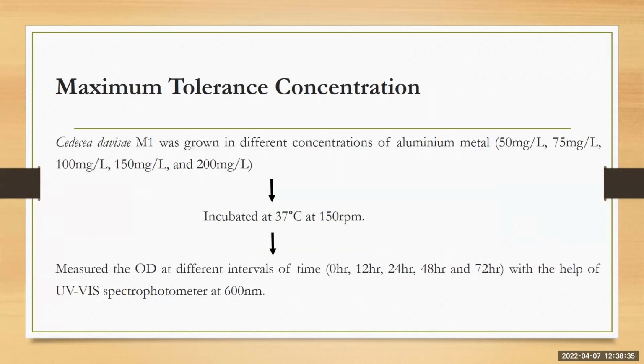After that, we have done the maximum tolerance concentration, that is, how much aluminium metal this bacteria can tolerate. For this, we have grown it in different concentrations of aluminium metal: first 50, 75, 100 mg per liter, then 150, and then 200, and also without metal. After that, we incubated at 37 degrees centigrade at 150 RPM, and then measured the OD at different intervals of time, like 0 hour, 12 hour, 24, 48, and 72 hours, with the help of a UV visible spectrophotometer at 600 nanometer.